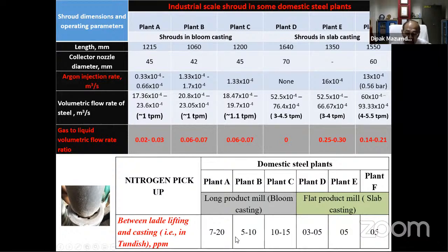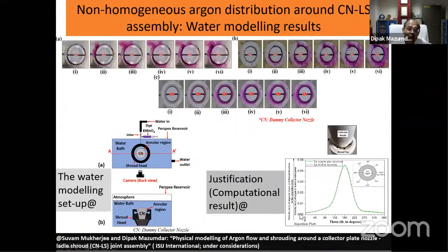And you can see here that there are different amounts of nitrogen pickup, whether there's no gas injection or varied gas injection, which essentially indicates that the shroud collector plate nozzle is really not perfect in the industry, and therefore, some oxygen is going to go in, some nitrogen is going in, and these are manifested consistently in the 6 different steel plants that we have considered. To verify this, this is the work of my doctoral student, we have taken cut pieces of ladle shroud of 3 different designs, and we have carried out dye tracer distribution by submerging the actual shroud heads in a water bath as it is indicated.